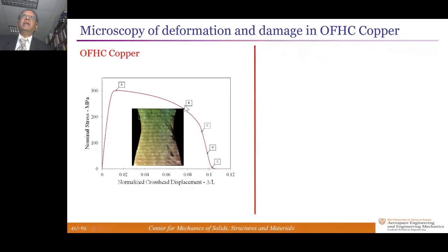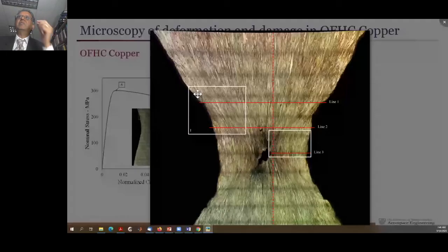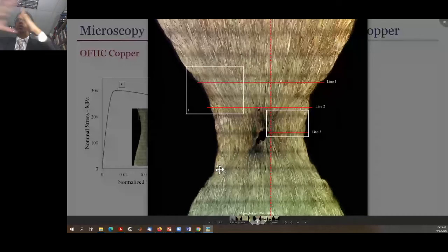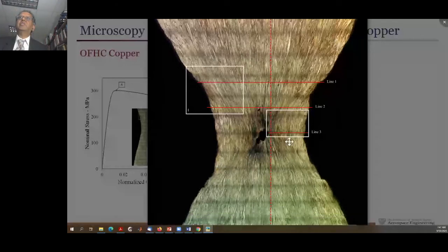If you come to this point at C, the neck has developed more. And I'll expand this. This is why I needed a second screen. You can see greater detail. I will zoom into something here. This is an image of every grain at every point of the cross-section. And you can measure the dimensional changes. And you could see a lot of other features that I'm not going to outline. For example, these are streamlines of the flow that I can identify from this. Streamlines break the surface, which means there's been a discontinuous event taking place. But if you squint your eye, you could see there's the formation of the shear band, two intersecting shear bands in the plane strain region of this specimen.